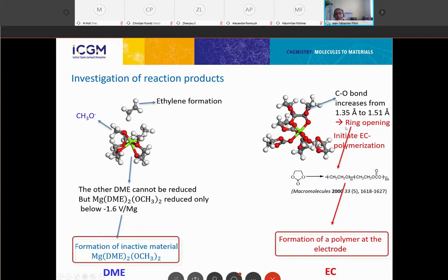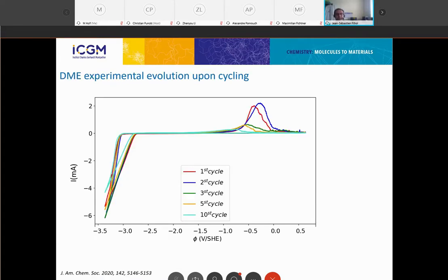In the second case, in the case of ethylene carbonate, we form the dimer, but what we see is a strong ring opening tendency. And when ethylene carbonates undergo ring openings, it tends to form a polymer. So the problem with ethylene carbonates, it should be a better solvent, but the problem is it's going to initiate a polymerization reaction at the electrode. That is not a very good idea because it's going to certainly passivate the electrodes.